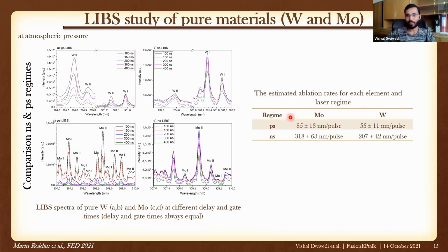We also tried to estimate ablation rates for each element and each laser regime. So we see in picosecond we have a lower ablation rate, here 85 and 55 for tungsten. And in nanosecond we have around 200 and 300 nanometer per pulse.